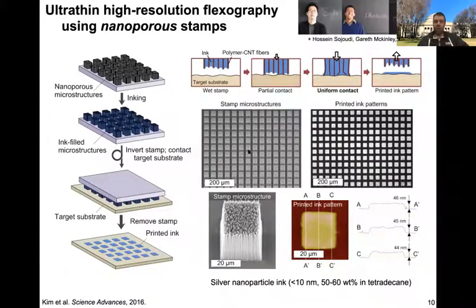So back to another version of the slide before the last one, where now you see the schematic of the process from left to right, and you see an example comparison of CNT stamp microstructures to printed ink patterns, and you see one stamp and one printed ink feature to show the fidelity we can achieve. What we saw early on, while we were still working out a lot of kinks and issues in uniformity, is that you can indeed get a printed ink pattern here measured by AFM to be very uniform. After drying of the liquid that contains the colloidal material in the ink. And you can also get it to have sharp corners, which is important if you're printing high fidelity features for sure.